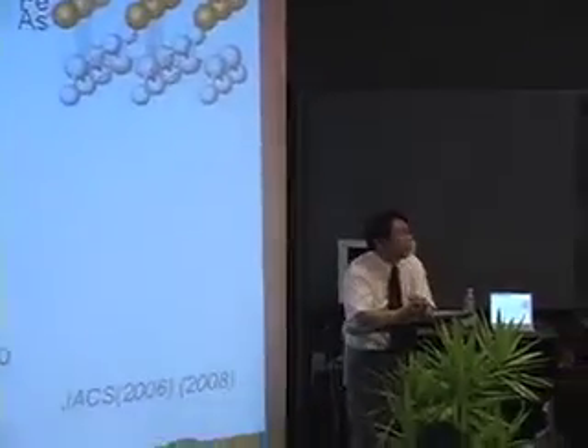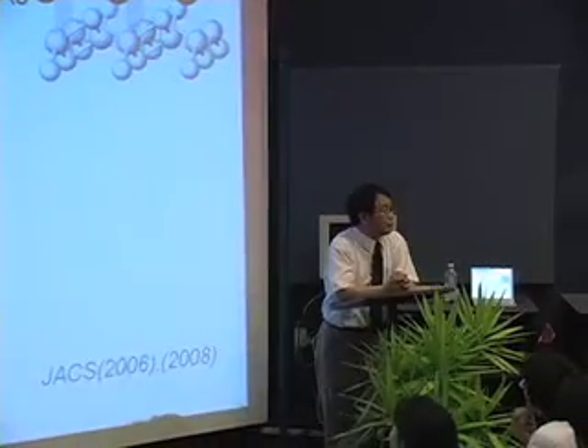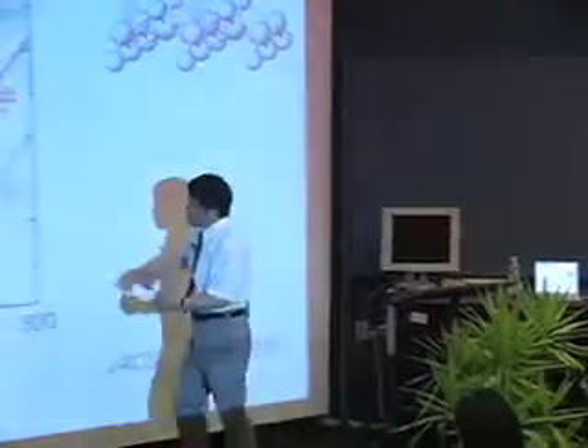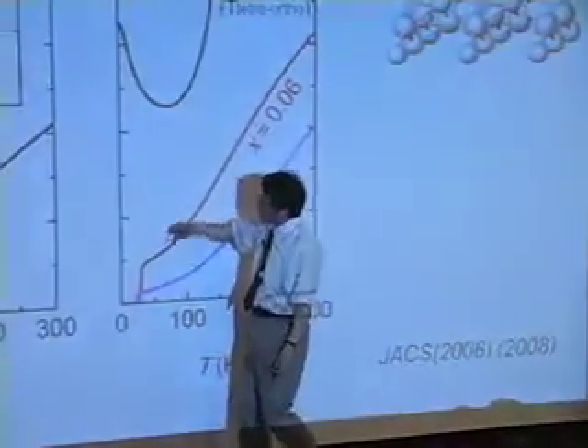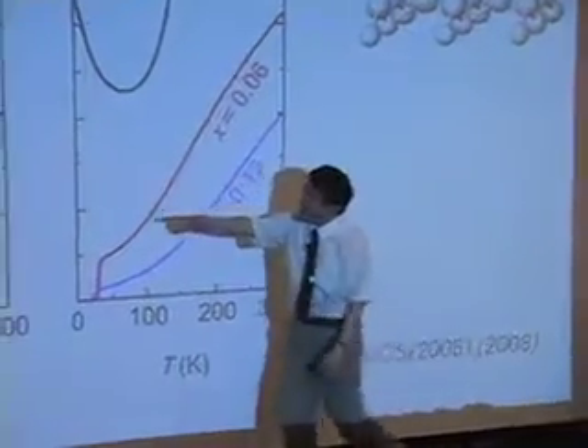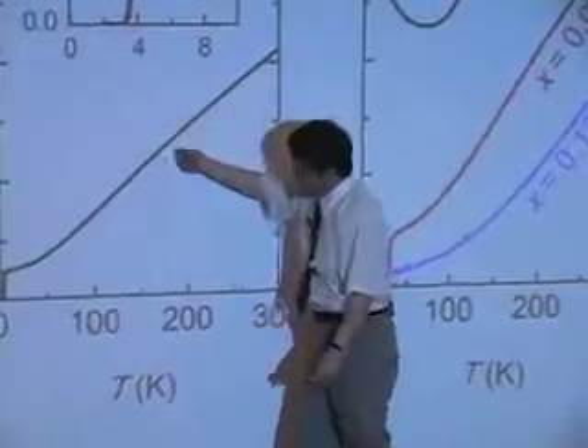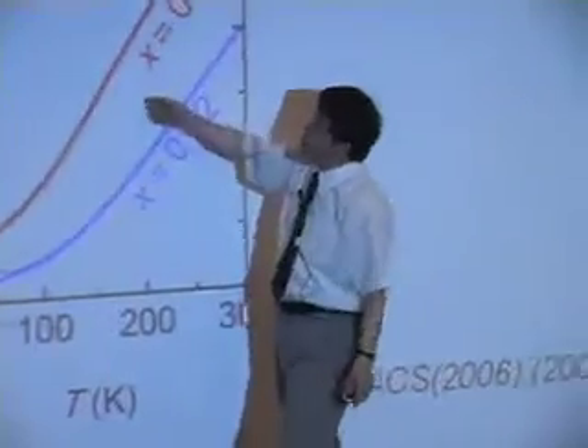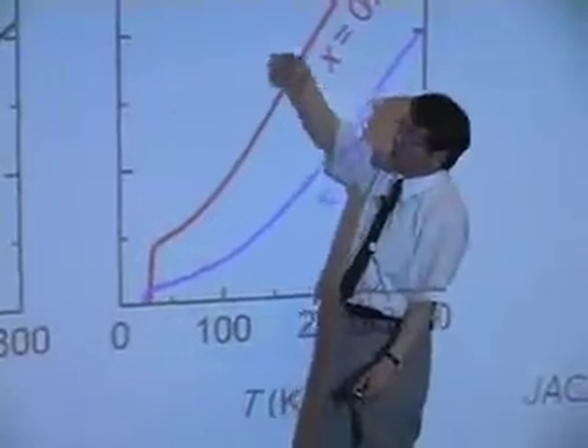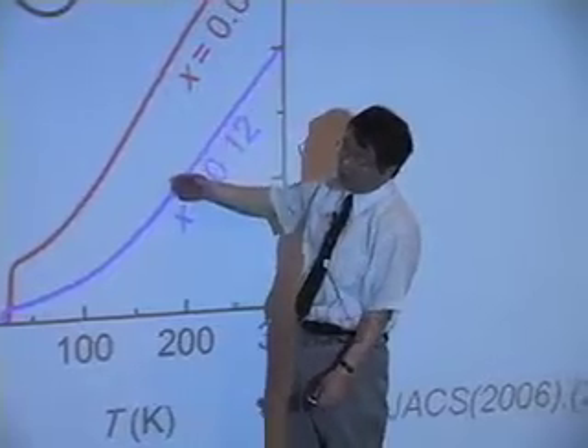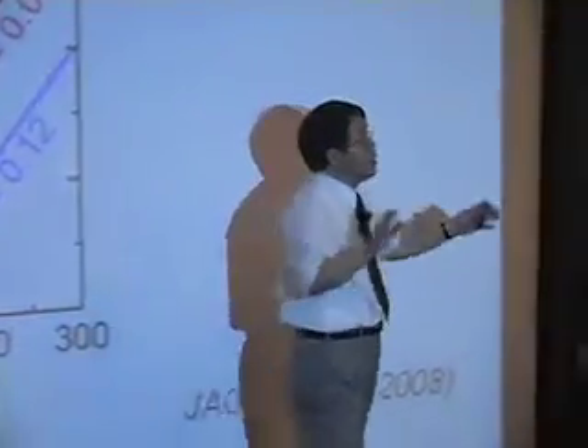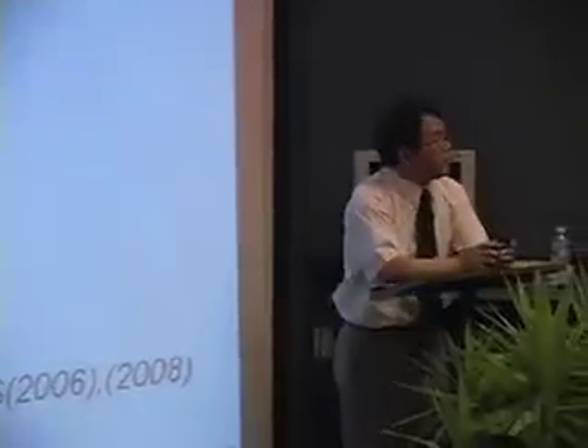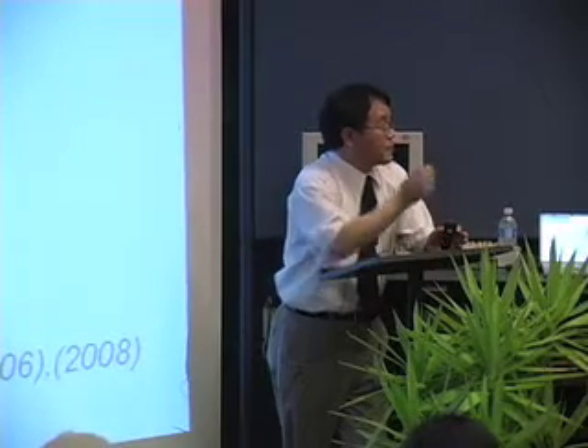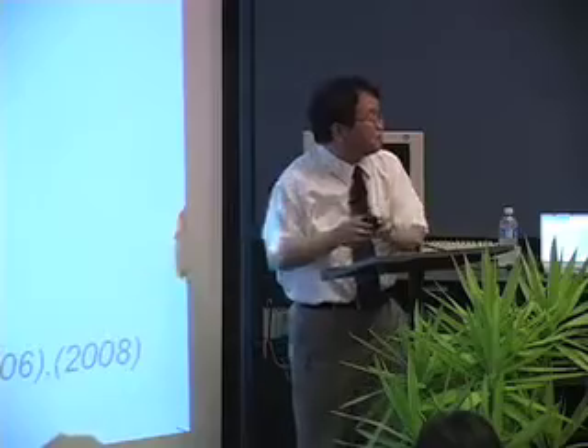The electron doping is very essential. The non-doped state we call the parent material. The parent material is not a superconductor, or if it is, the TC is low. But when carriers are doped, TC becomes high. This is pretty much the case of the cuprates. The parent material of the cuprate is an insulator. When holes are doped, superconductivity comes out.